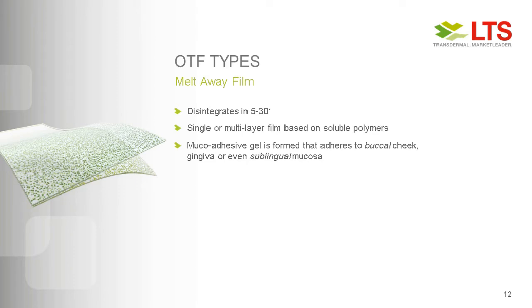The second type of OTFs are so-called melt-away films. They do disintegrate within several minutes, so in the range maybe of 5 to 30 minutes. And this can be tailored based on the target product profile that your product should have. These films are mainly applied in the buccal cheek, and they consist of a single-layer or multi-layer film, also based on soluble polymers, but of course not so highly soluble as for the fast disintegrating films. What also can be done is that this film forms a mucoadhesive gel after being applied in the buccal cheek, and there it stays and releases the drug very slowly into the oral cavity. The same type also can even be used for a sublingual application.